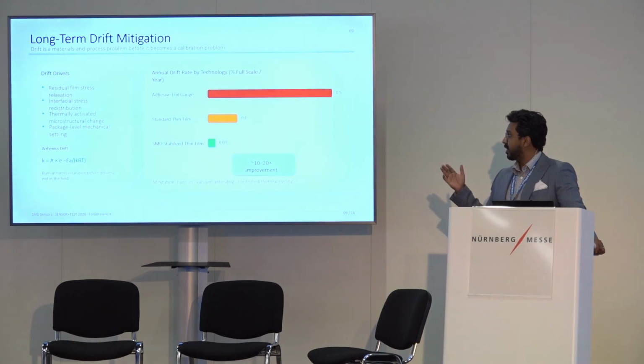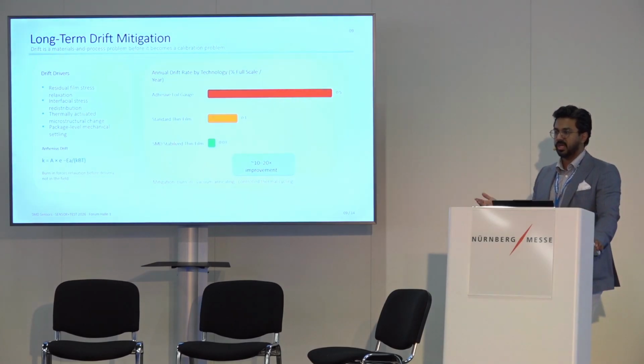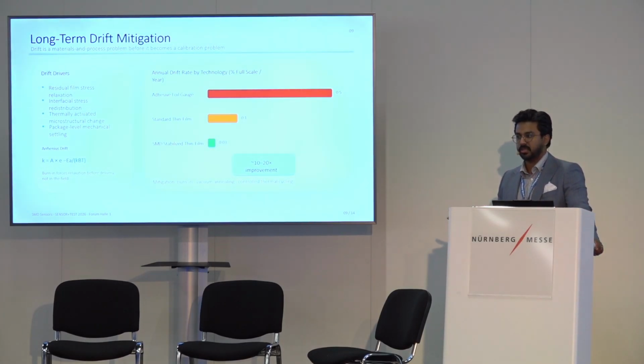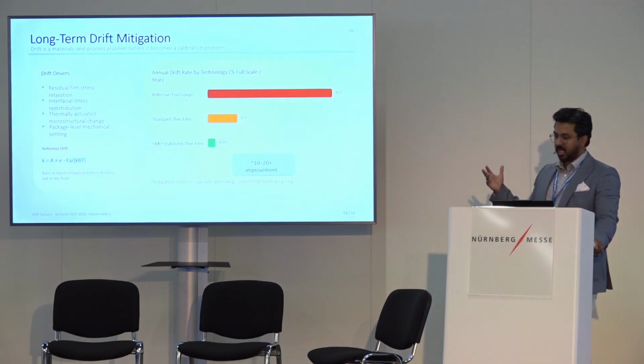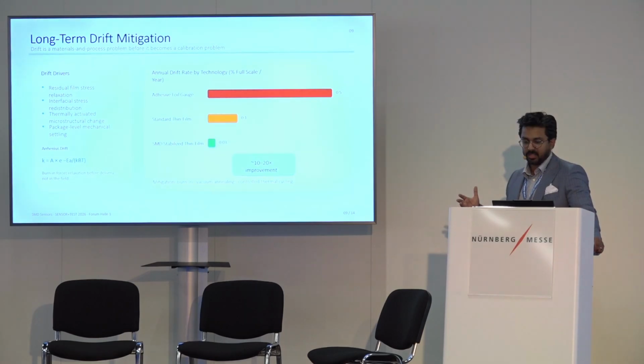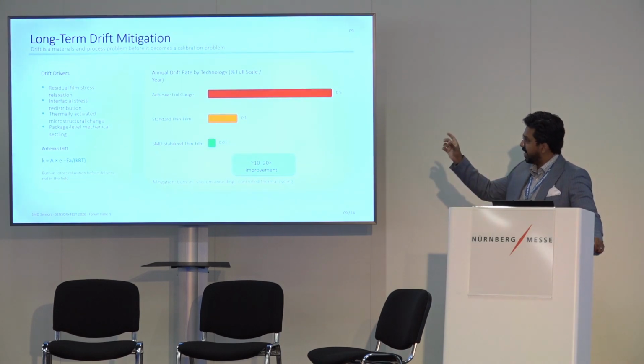So if we don't figure out that these drifts happen, we don't necessarily know over the long term. After 2 years, you won't see the drift. If you are expecting a sensor to perform for 30 years and 2 years in it starts to drop on results, you wouldn't be able to figure it out and condition monitor for a very long time. So we have to look into these elements, and we do this. We check the Arrhenius equation, which explains the drift.